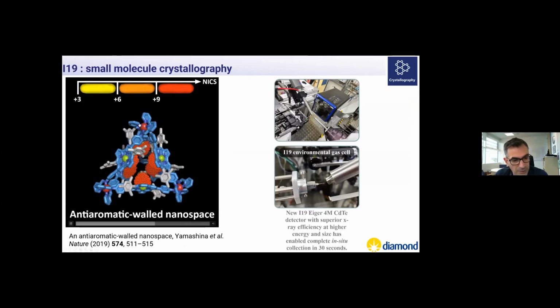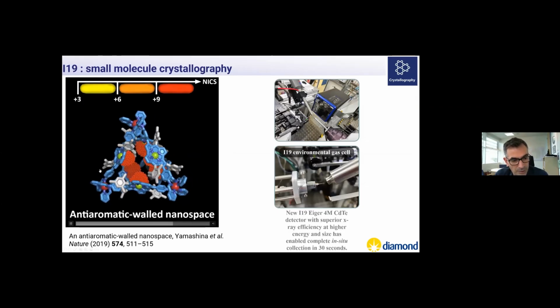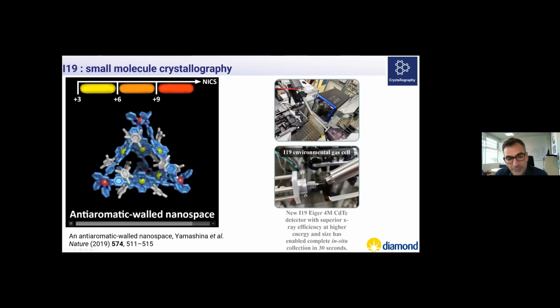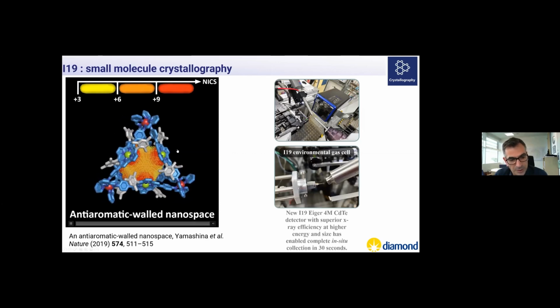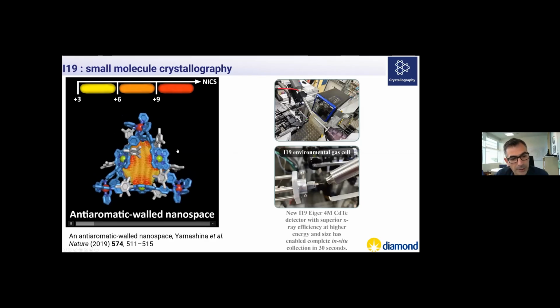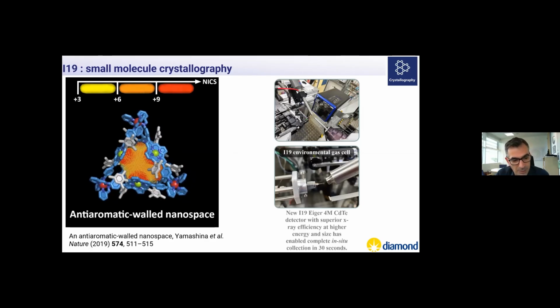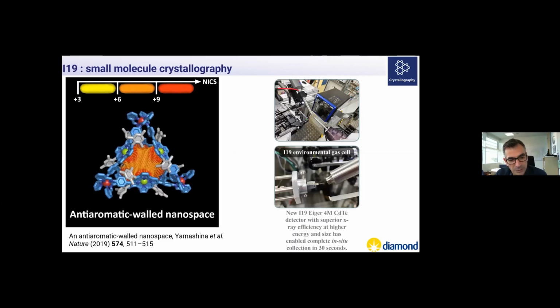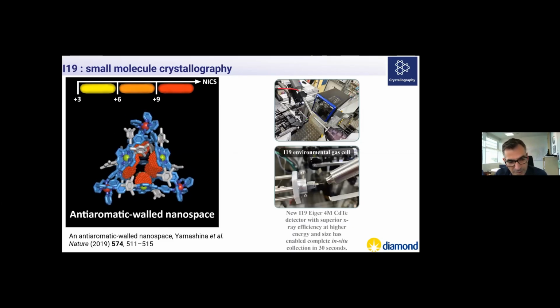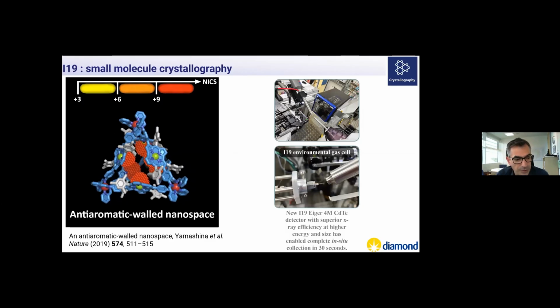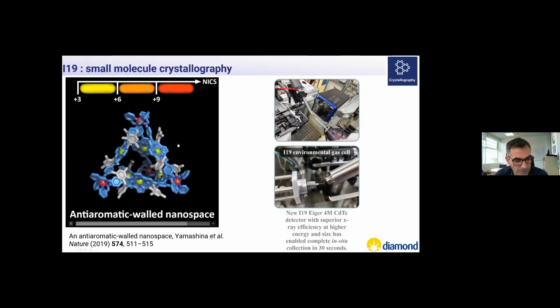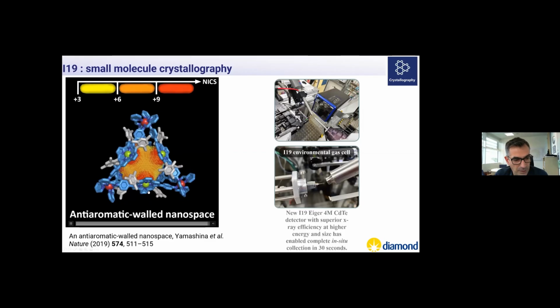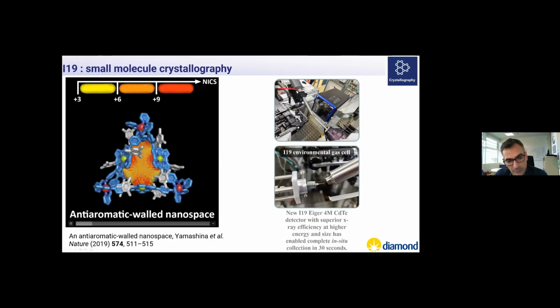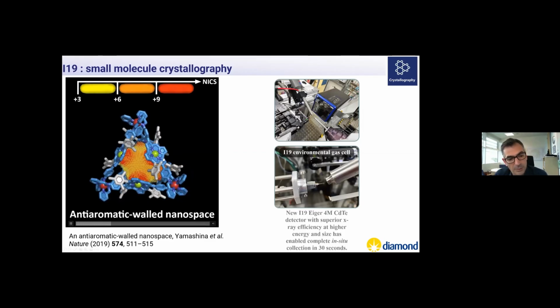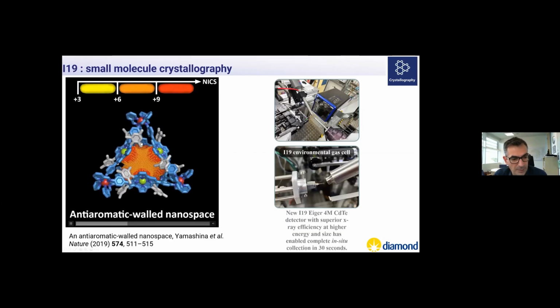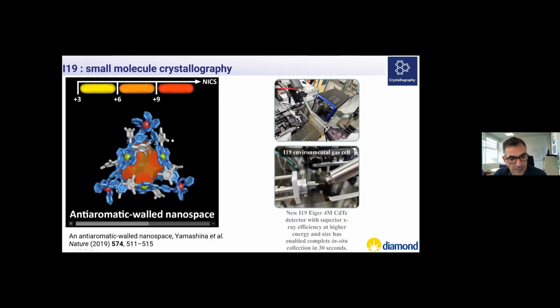This was one of the first structures actually collected after we installed the robot, which is essentially a copy and a translation of what has happened in the field of macromolecular crystallography to chemical crystallography, where we have higher and higher throughput. And this first structure was very interesting. It's an anti-aromatic wall nanospace. These are usually structures that are very reactive and very unstable, but they were able to stabilize this structure and collect the data on I-19.